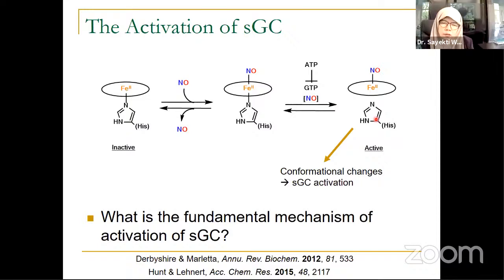Especially if replaced with carbonyl. Yeah, with carbonyl, there's no activation because this 6-coordinate complex is stable. No further reaction happens, and so that means there's no activation. You have to break the bond to the histidine in order to get the activation, and only NO can do that because of its special electronic effect.